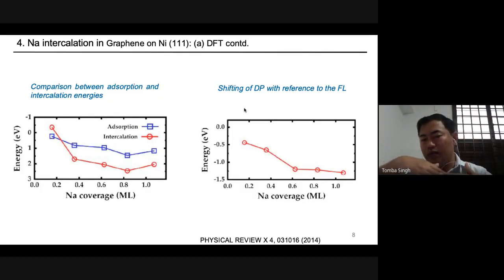As we are sure that there is a possibility of intercalation, then definitely we can see the Dirac point. In this curve, we want to see the movement of the Dirac point with respect to the Fermi level. We see here at low coverage, the Dirac point is visible. Then with the increase of the sodium coverage, it goes down very quickly. Then around 0.63, the Dirac point remains stable. So we don't need more addition of sodium. This coverage, 0.63 monolayer, is taken as a reference, and for the calculation and for the experiment, we'll try to keep this 0.63 monolayer coverage.